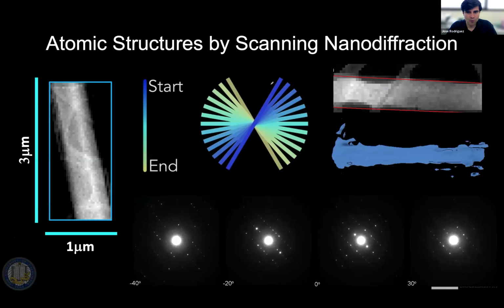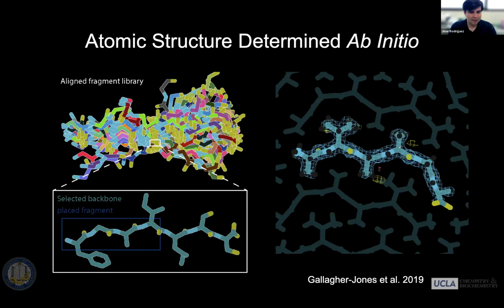So we can raster scan that as we will, and that gives us the ability to ex post facto identify subregions of the crystal that we're particularly interested in and integrate the diffraction just from those regions in 3 dimensions. We're, of course, collecting a 4D STEM scan at various angles as we tilt the sample from typically something like plus or minus 40 or 50 degrees. And when we do that, we're able to map in 3 dimensions where we want our crystal, where we want our signal to come from, so we can identify the bounds of the crystal or a subregion of the crystal. Here are some synthetic diffraction patterns that have been coalesced from the individual diffraction data that is summed together or averaged together. And so after doing all of that, we're able to take all the diffraction data and determine an atomic structure from it. So this is the atomic structure of a peptide from a crystal that was illuminated by 4D STEM here.